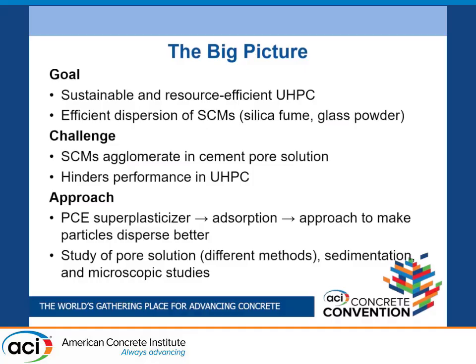But these supplementary cementitious materials tend to agglomerate in the cement pore solution. That is, they tend to form clusters, which reduces the reactivity of the UHPC, and they do not give a satisfying performance.